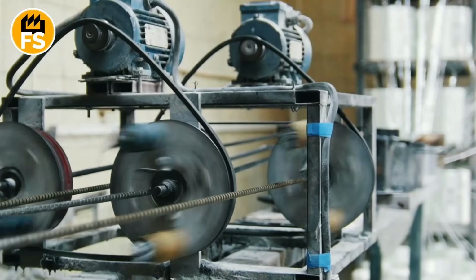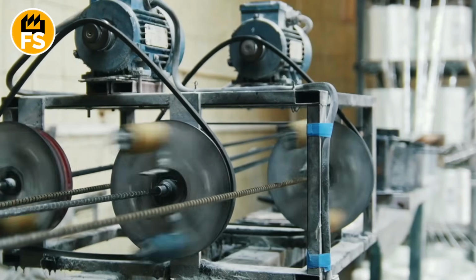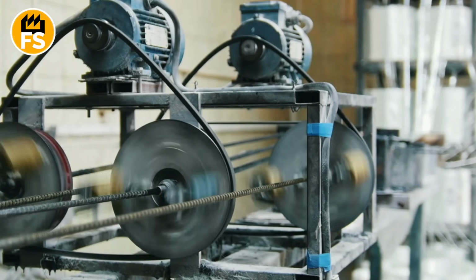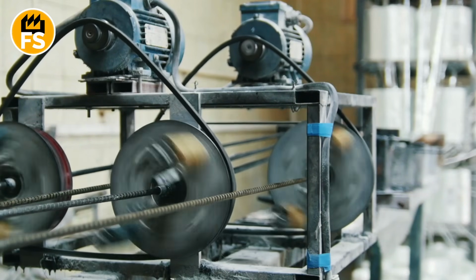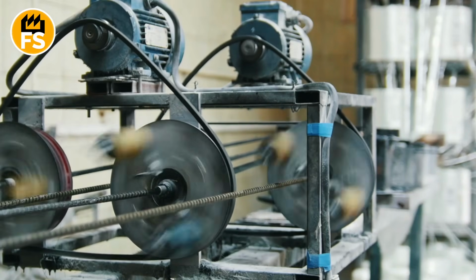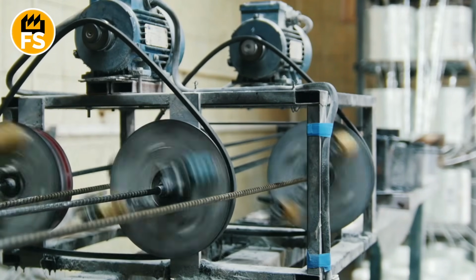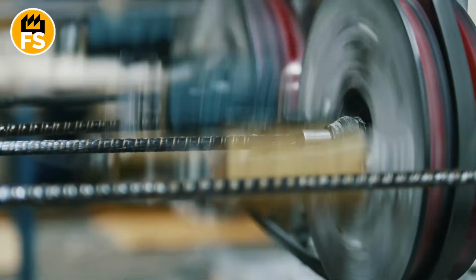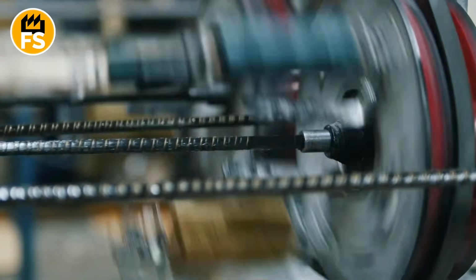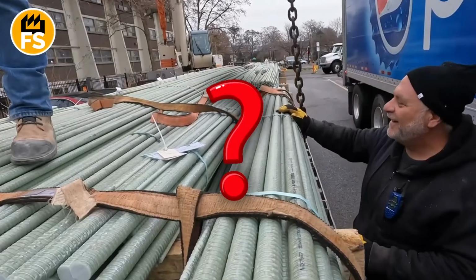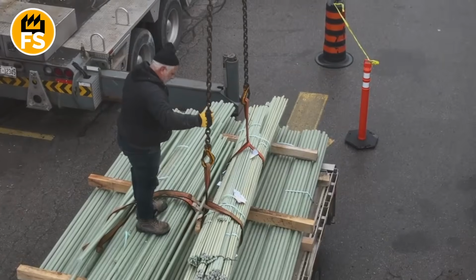Second, it tightly compresses all the fiberglass together, forming a perfectly round rod. Third, the heat from the die starts the initial stage of the chemical reaction of hardening, or polymerization. The resin begins to turn from a liquid into a gel. At the exit of the die, we already see the familiar shape of the rod, but it is still soft and vulnerable. But how does it get its famous ribbed surface to hold well in concrete?